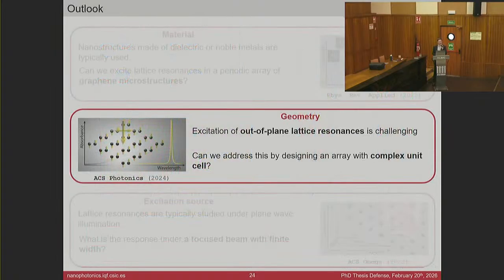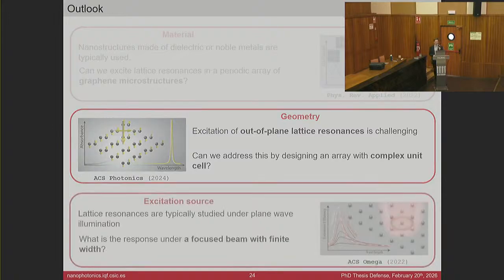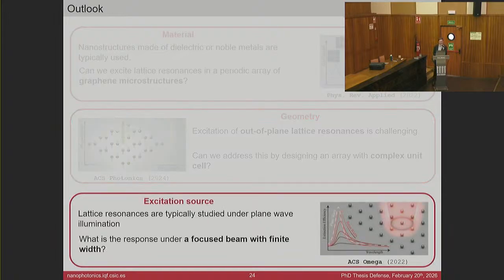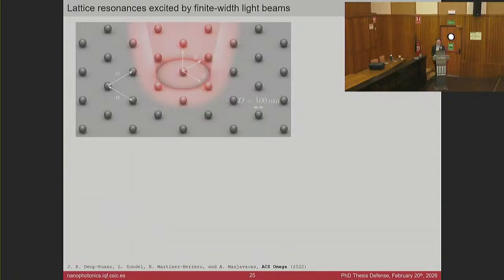Now, I have shown you how we can obtain lattice resonances with new materials and new effects arising from the geometry. But something really interesting and crucial, I will say, that maybe was missing in the literature is an analysis of the role of the excitation source, of how we excite these resonances. Because most studies just focus on plane wave illumination. And this is just an approximation. It's not something that we can actually produce. So what is the actual role of an excitation source that has a finite size? And when do we approach this plane wave limit?